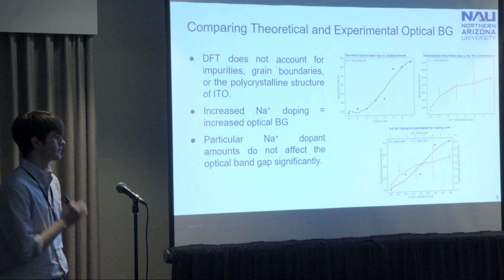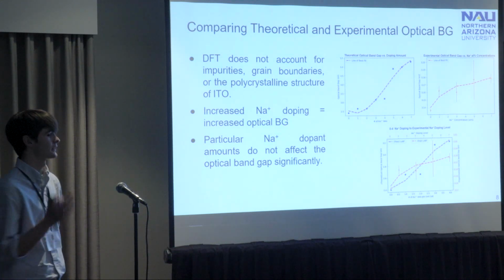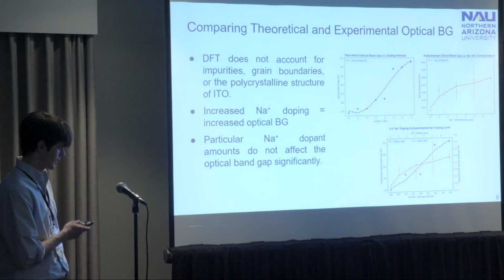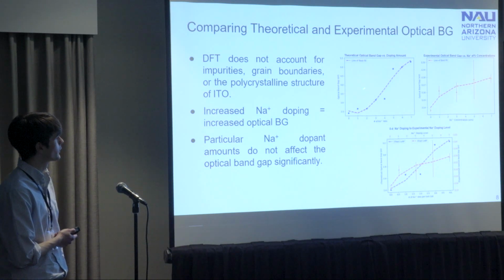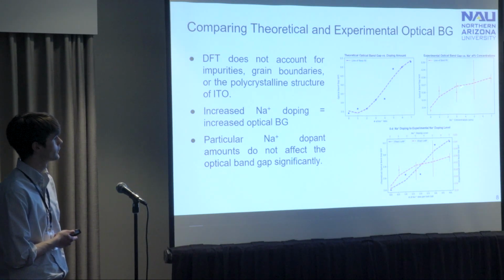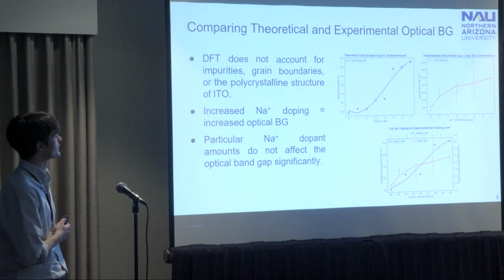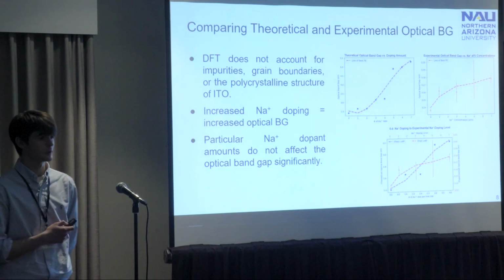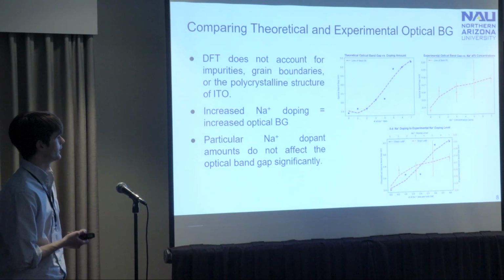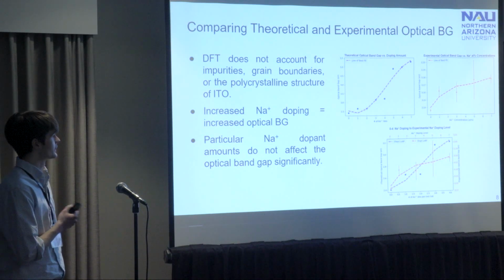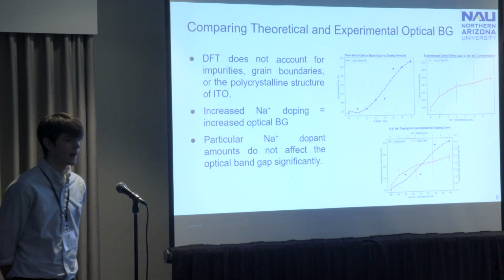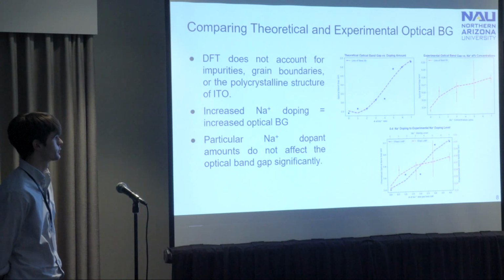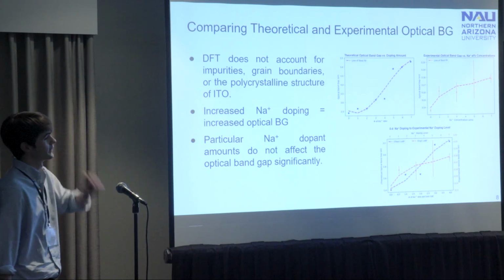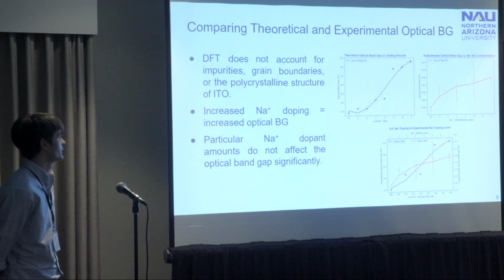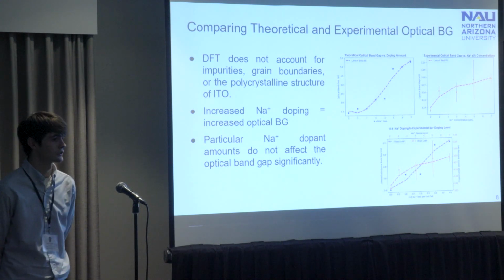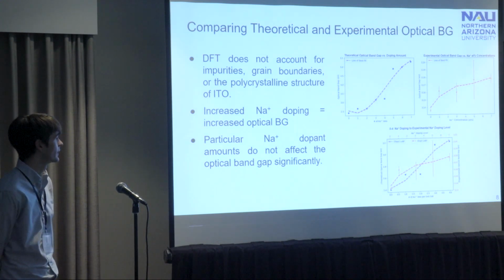So to combine the theoretically found optical band gap to the experimentally found optical band gap from my Tauc plots, we have these two plots here where purple and blue correspond to the theoretical optical band gap and orange corresponds to the experimental. As you can see, DFT would not be the greatest predictor of the optical band gap. This is because the DFT calculations were done on an isolated ITO unit cell where bulk factors were not taken into account, which have a heavy influence on the optical band gap, such as impurities, grain boundaries, and the polycrystalline structure of ITO affecting that optical band gap.